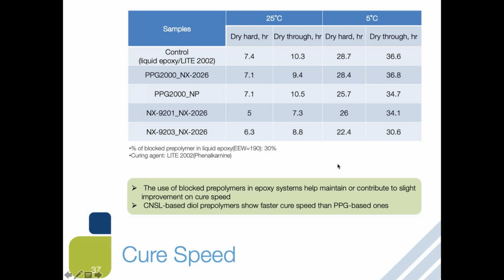Then we measure the cure speed using dry hard and dry through at 2 different temperatures. So as you can see, if you compare cure speed from the control to the other systems, in general, adding 30%, which is a sizable amount, of this prepolymer did not reduce the cure speed, and actually rather improved the cure speed in some cases, especially with the NX-9203 CNSL-based diol prepolymer system.